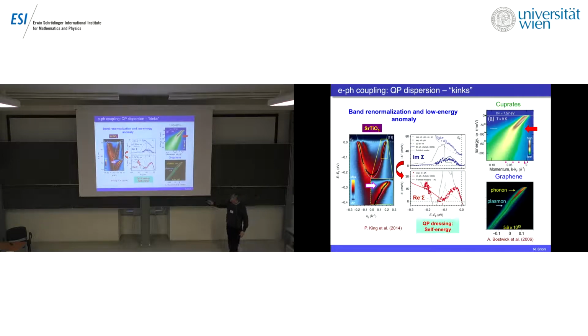Now, this is not just a case of strontium titanate. It's fairly ubiquitous. In particular, in cuprate systems, there have been a lot of studies showing this kink, which may or may not actually be a phonon effect. I mean, it just tells you that there is a coupling to some boson. It may be something else, but there are different schools or different churches about this. This is the case of graphene, which is somewhat more interesting because you have two kinks. People believe that there is a coupling to a phonon and then a coupling to a plasmon. So each one at its own energy, and each one giving a specific kink.